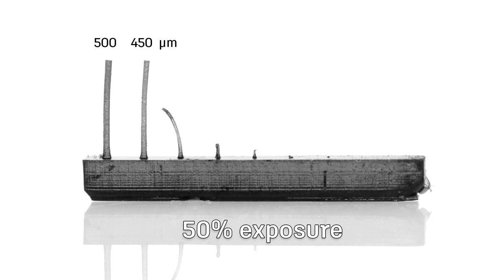With half the light energy as the original print, only the 500 and 450 micron posts form, but they're thinner than they should be.